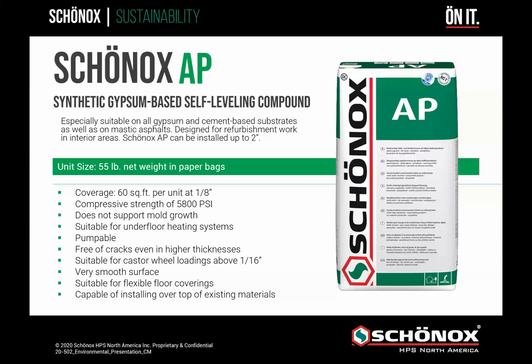Over your VCT, the vinyl asbestos tile, the mastic, the wood floor, and in historical renovations, Schönox AP can be installed from a 1/16 of an inch all the way up to 2 inches in one lift. It's suitable for underfloor heating systems. It's pumpable. It's very smooth. Gives us the ability for caster loadings at a 1/16 of an inch, and it's suitable for most flexible floor coverings. So Schönox AP is a perfect way to reuse that existing facility without doing demolition.